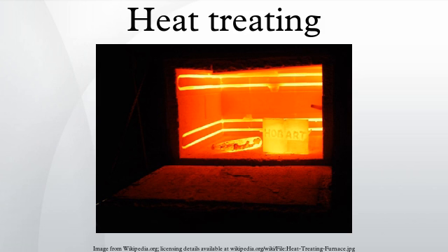The tempering colors can be used to judge the final properties of the tempered steel. Very hard tool steel is often tempered in the light to dark straw range, whereas spring steel is often tempered to the blue. However, the final hardness of the tempered steel will vary, depending on the composition of the steel.